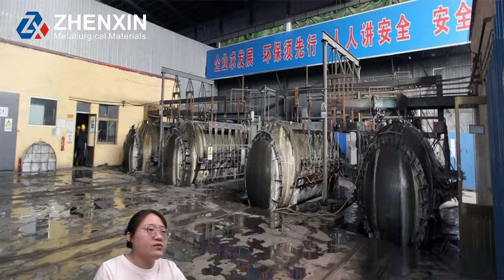Yes, and one of our recent shipments to South Asia highlighted the practical benefit of ferrosilicon nitride. The steel mill had been struggling with uneven nitrogen recovery using traditional methods. After trialing our ferrosilicon nitride, they reported more stable nitrogen levels and improved toughness in their end products. What impressed them most, however, was the cost saving. It is estimated at an 8 to 10% reduction in alloying expenses compared to their previous practice.